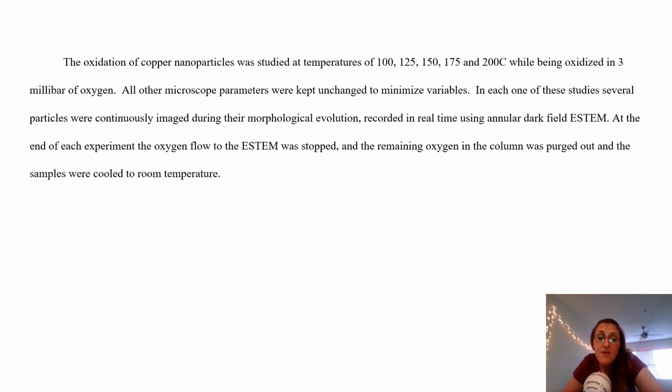The oxidation of copper nanoparticles was studied at temperatures of 100, 125, 150, 175, and 200 degrees Celsius while being oxidized in 3 millibar of oxygen. All other microscope parameters were kept unchanged to minimize variables. In each of these studies, several particles were continuously imaged during their morphological evolution, recorded in real time using annular